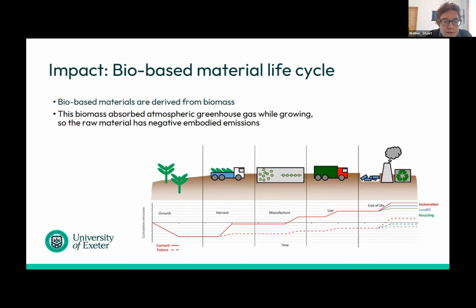So maybe around the manufacture phase, we end up with a net zero emission, and then as we go through use and end of life treatment, we again cause some more impacts. But if we can reduce those middle phases sufficiently, we can lower that line down, and you could in theory end up with a material that can get to the use phase and still have a net negative emission. So it can be effectively sequestered greenhouse gas at the point of use, in theory.